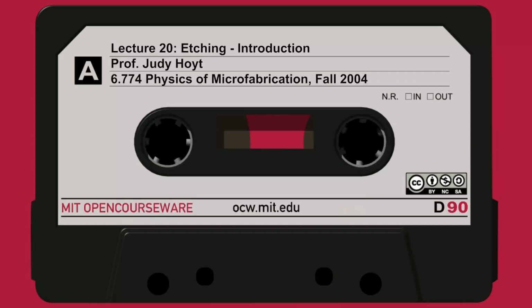So the first thing we want to figure out is how much of an over-etch is required. And we usually represent over-etch as a percent of the total time. So if I'm going to etch for a minute to get rid of the film, and then I leave it in an extra minute to make sure that I've taken care of non-uniformities, that's called 100% over-etch, because it's 100% of the main etch time. I'm contributing 100% of that to the over-etch step. So we want to know how much over-etch is required as a percent in order to make sure that all the oxide on the wafer that you etched all the way down at every point in the wafer.